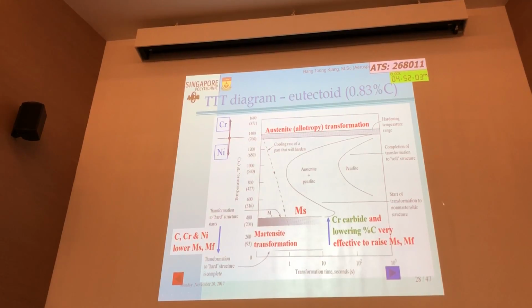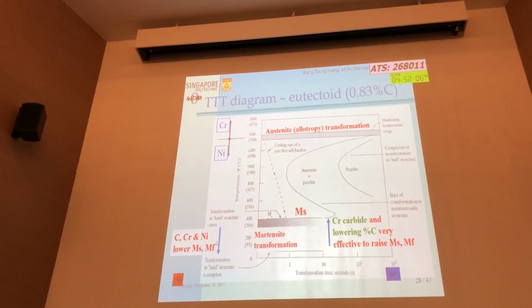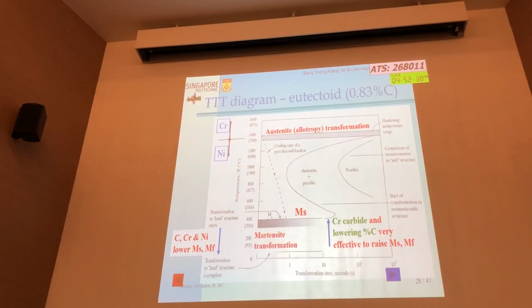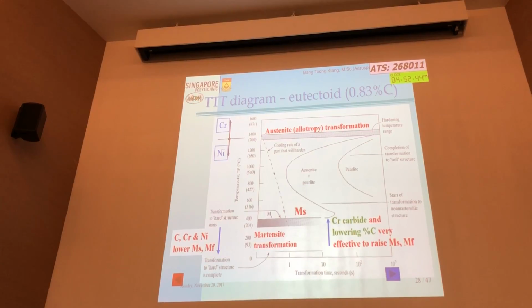So the thinking is, we add nickel to give me austenite, but that makes heat treatment impossible. So we remove some nickel, at least to raise the MS line. It's still below room temperature, but at least we raise it some. The other way to further raise it is to create chromium carbide, so as to further raise the MS temperature to allow it to be heat treatable. So that is the principle behind precipitation hardened stainless steel.